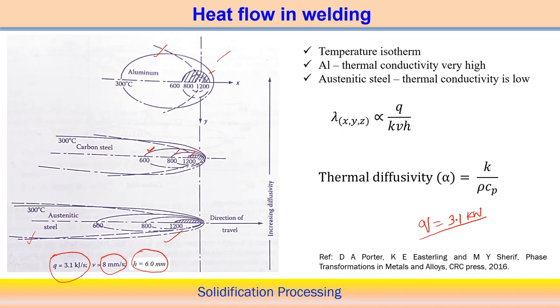Now of course in this figure, apart from thermal conductivity, we also see the thermal diffusivity. If there is an increasing thermal diffusivity, the temperature profile is actually changing. Thermal diffusivity is the thermal conductivity divided by the density and specific heat. That ratio indicates the thermal diffusivity. Usually if conductivity is very high and density and specific heat are low, that kind of material has very good thermal diffusivity. Aluminium has very high thermal diffusivity as well as high thermal conductivity as compared to austenitic stainless steel, and we get temperature isotherms and profiles from the analytical solution that are completely different.